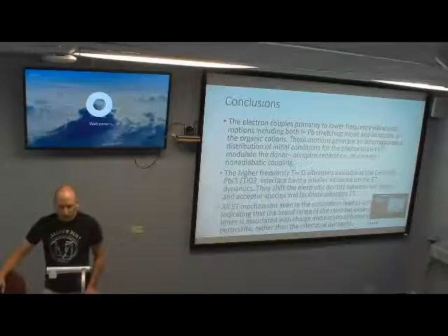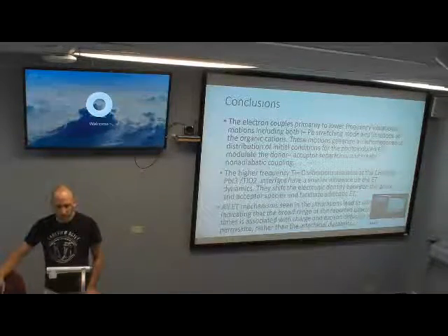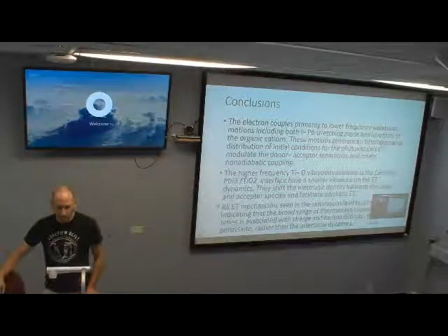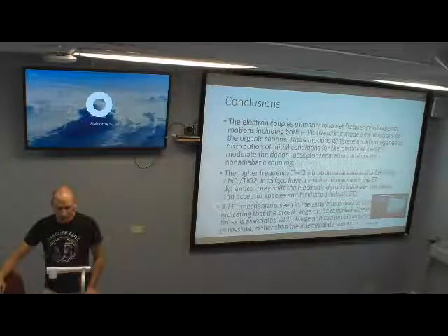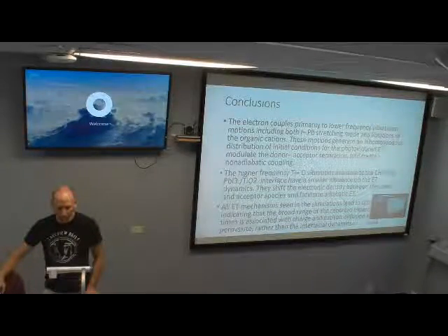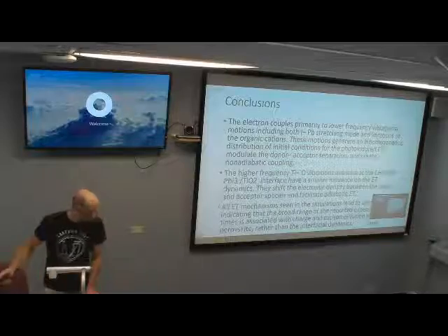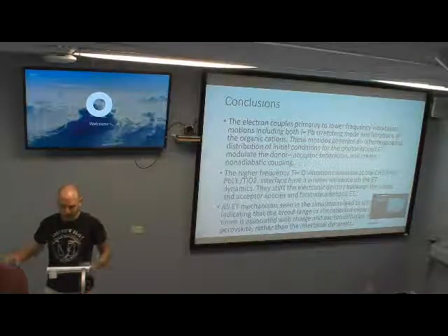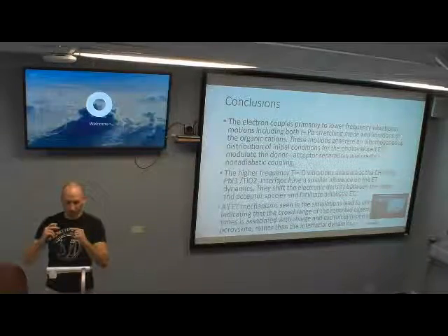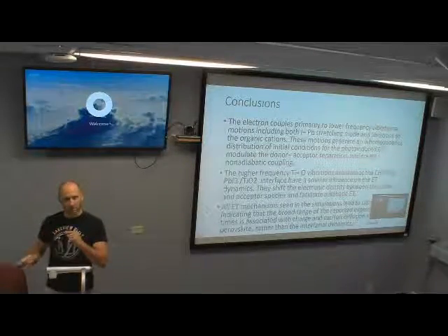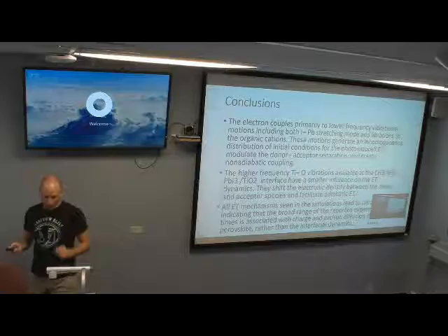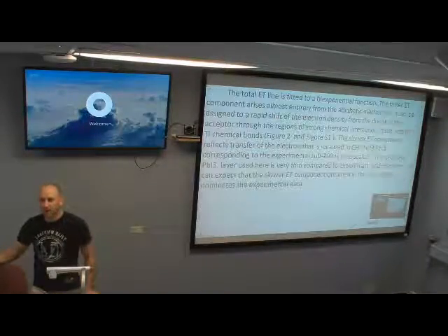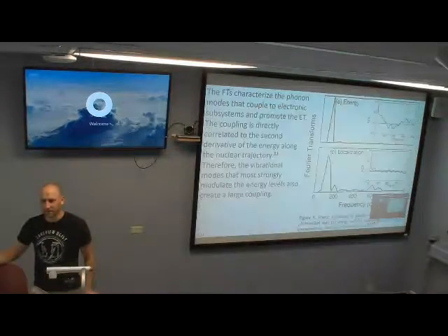But what do you think about the size of the system? The perovskite is way too thin. And what about titanium dioxide? It's probably even thinner than the perovskite. In the model that they show, the perovskite is literally one layer, and titanium is the same, or maybe two layers. Well, it goes off the edge of the screen. How many atomic layers do they have in the titanium dioxide along the Z direction, which is the charge transfer direction?